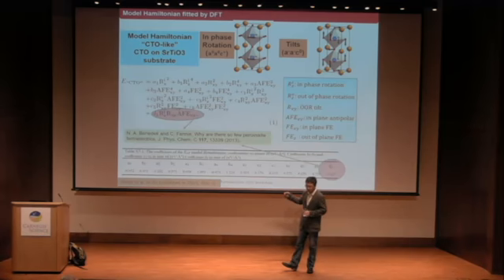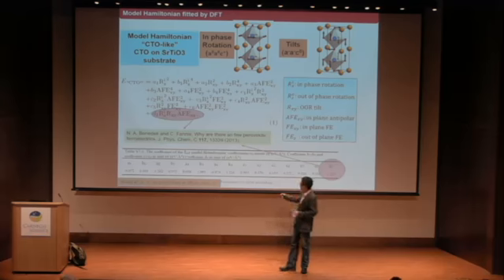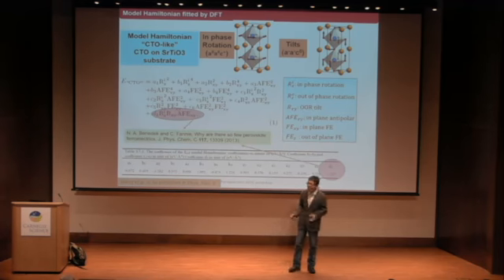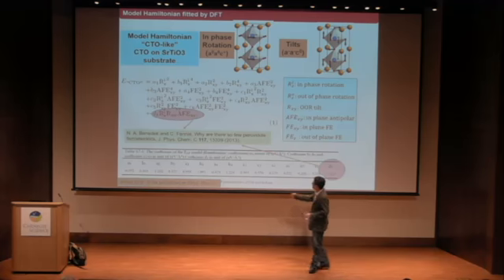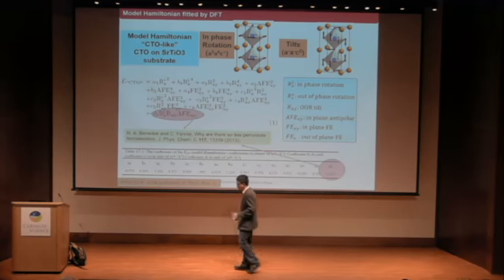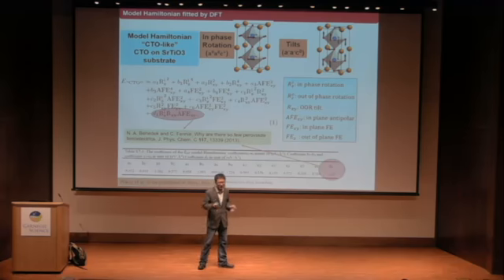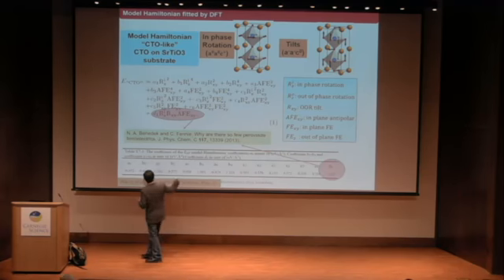the so-called hybrid improper ferroelectrics. This term was also proposed before by Nicole and Craig. You can see this term has a large negative coefficient, which means that this term wants to lower the energy to stabilize in this so-called antipolar mode.